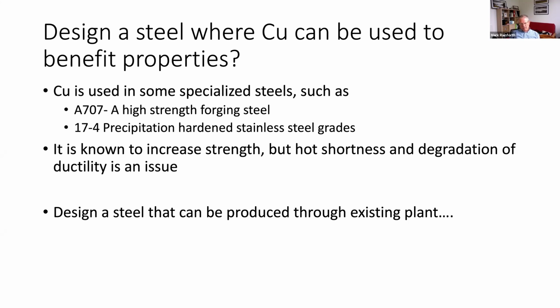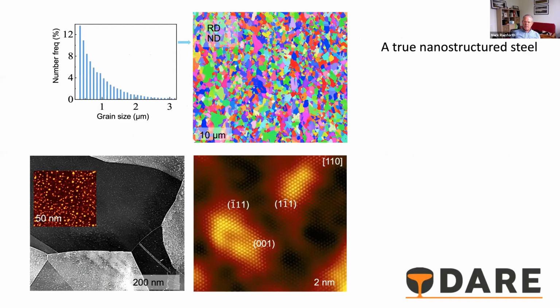So as I say, we had a project to try and think laterally about whether we could develop a steel that could be made relatively straightforwardly, that could deliver on our challenges of having high strength, be made on existing plant, be processable, and be within at least the same cost, or if not reduced cost. And I don't have time to go through the rather interesting story and the way we went, but we started taking a baseline of an iron manganese steel, and we started putting in copper in amounts of 1, 2, and 3%, up to 4% in fact, expecting the thing would just fall apart and it would all be a nightmare.